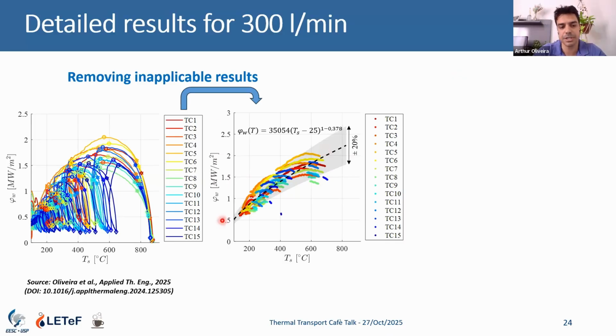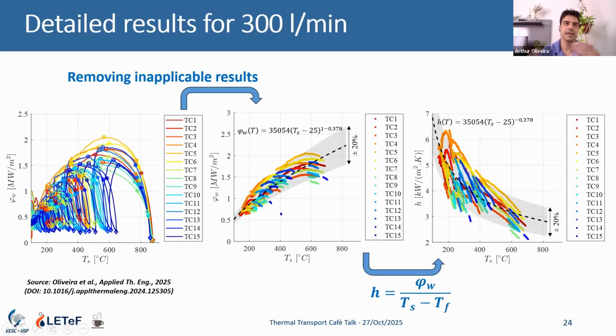So when we do this on our boiling curve and remove the unphysical data, now we have a kind of correlation between the heat flux and the surface temperature. We can try to fit an equation here to relate the heat flux and temperature, and we can also translate that to heat transfer coefficient, depending on the industrial partner's preference.